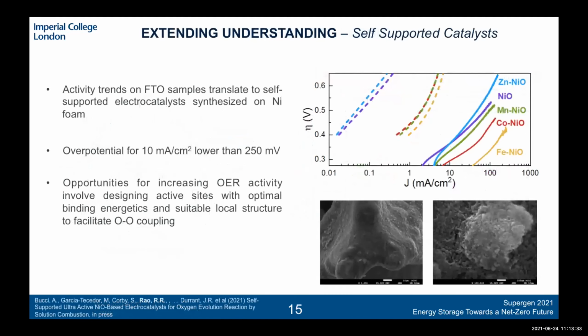So the final thing that we wanted to do is see how valid this learning was, from a really lab scale setup to a more industrially relevant catalytic structure. So we then deposited these catalysts on a 3-dimensional nickel foam, which would be something that would be more applicable to large scale water electrolysis because you have this really larger surface area of the nickel foam. And what's quite interesting to see is that the same activity trends that hold at the lab scale, where we had deposited this on ideal substrates where we can look at all of these fundamental studies, holds true even when you have these 3-dimensional nickel foam structures.